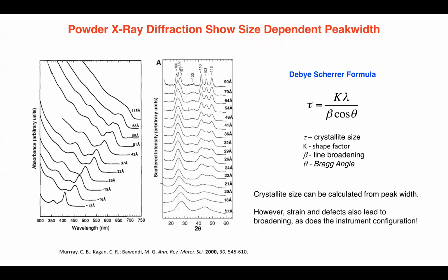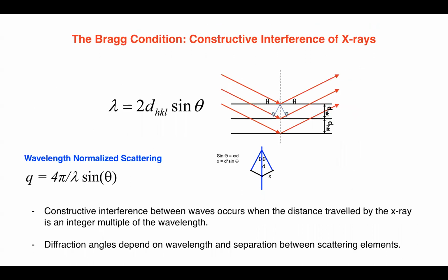It's not totally straightforward, but it's pretty straightforward to look at this and see that at 9 nanometers out here, there's still a fair amount of broadening in that pattern. This is the size range people are mostly interested in. So you can look at an X-ray pattern and size up your crystals this way. This is one of the ways to monitor crystal growth.